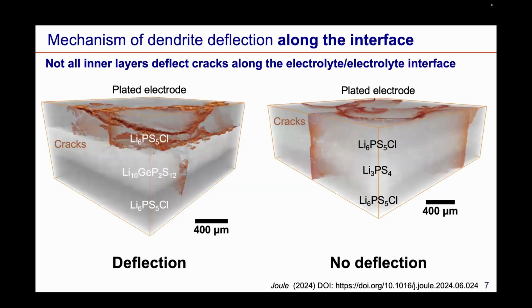Now let's consider the second type of deflection, which happens along the interface between the electrolytes. We replace the inner layer by a lithium germanium phosphorus sulfur, or LGPS, and also lithium phosphorus sulfur, LPS, and we image the dendritic cracks within the electrolyte by XCT. These 3D rendered XCT images show that dendritic crack can be deflected along the interface between the LPSC and LGPS, while there is no deflection when adopting LPS as the inner layer. So this says that not all inner layers can deflect crack along the interface.